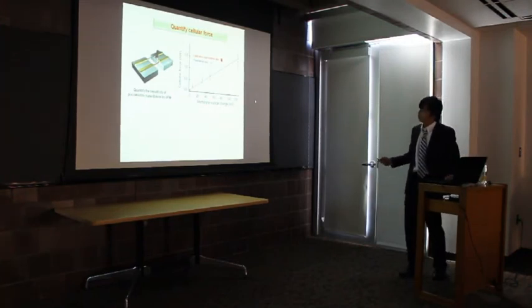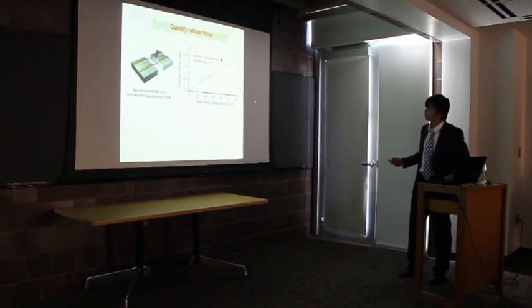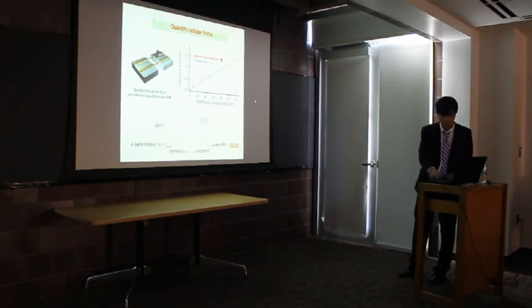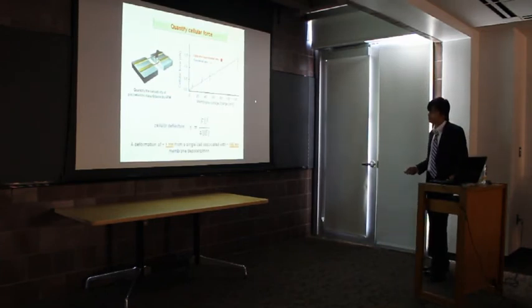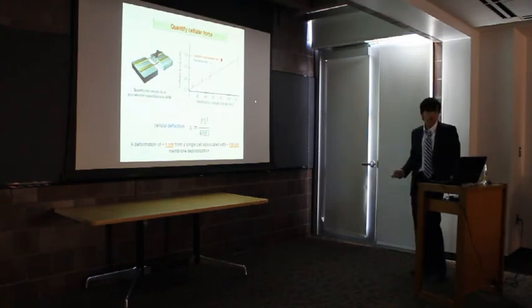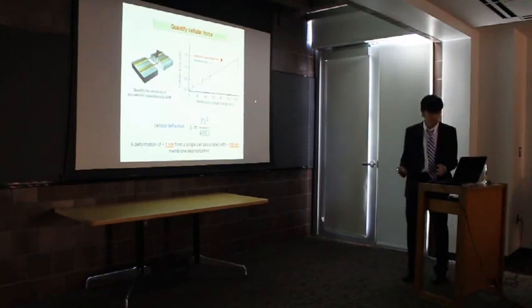And compared to the theoretical data from the last slide I showed you, it shows a really good fit between the theories and the experiments. And we can go further to estimate how much deflection the cell indeed has on the PZT nanoribbons. Using just a simple beam theory, we can get a very small deformation, about 1 nanometer from a single cell upon 100 millivolt membrane depolarization. They show you the very small deformations, and the PZT indeed has a very high sensitivity to sense the deformations.